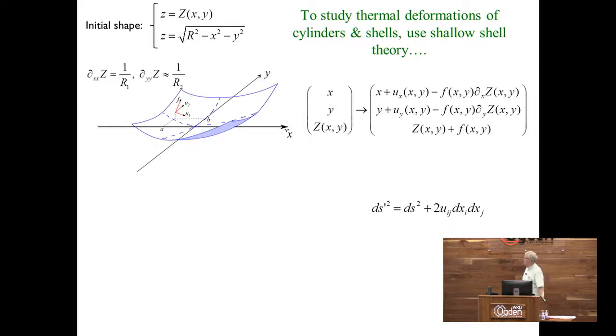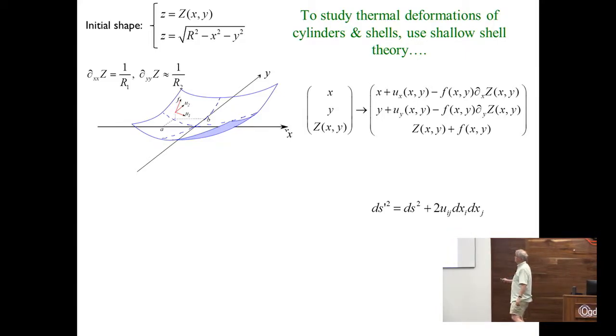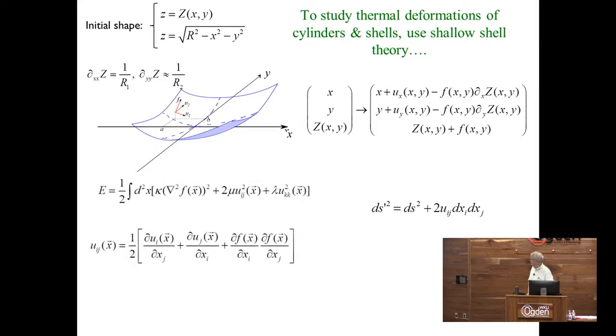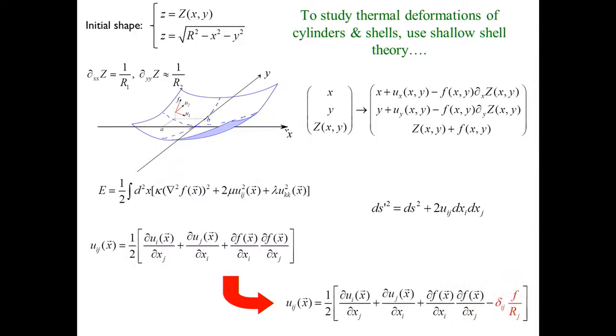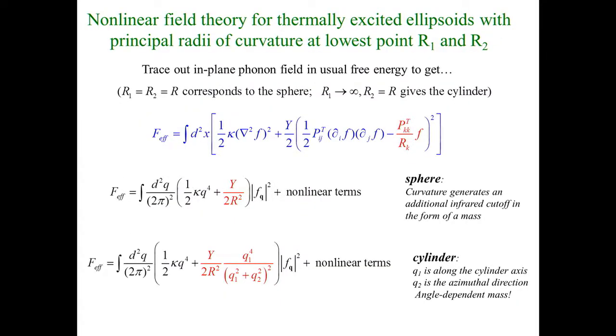And I'll just briefly sketch the math. There's something called shallow shell theory, which you can do with two locally different radii of curvature, or Gaussian principal curvatures here, 1 over R1, 1 over R2. And you go through the same math that I've been using to describe what's going on in these ribbons. And you find it's the same stress tensor, the same stuff, except there's a new term, which depends on F linearly. It breaks the symmetry. Positive F is different than negative F, as you might expect if there's a background Gaussian curvature or even a background cylindrical curvature. And the extra term goes like 1 over the radius of curvature, the principal curvature at that point. And if you work through the math, as I close up here, you discover that massless field theory requires a new term.